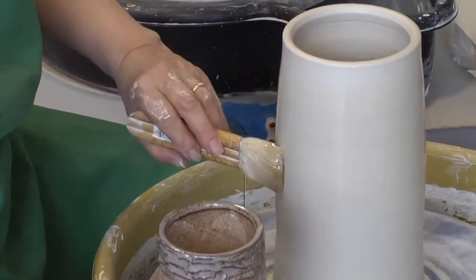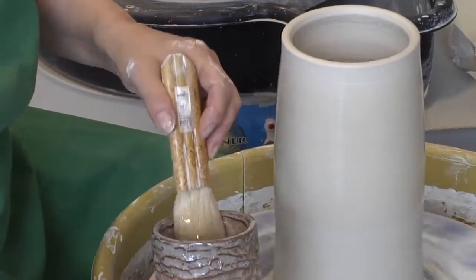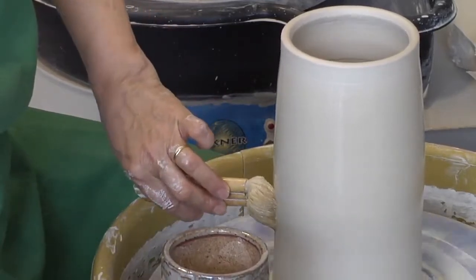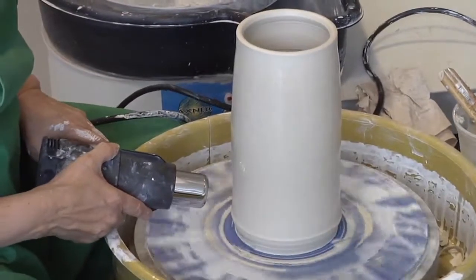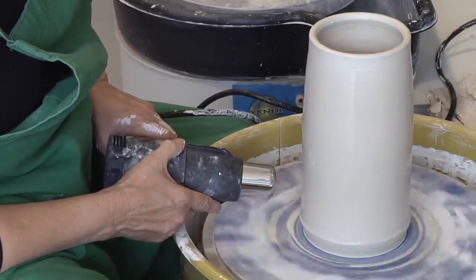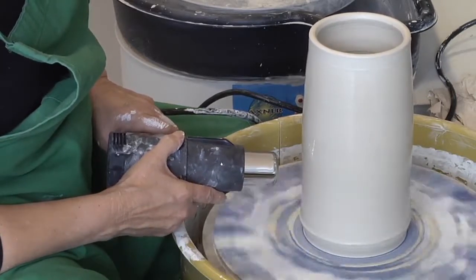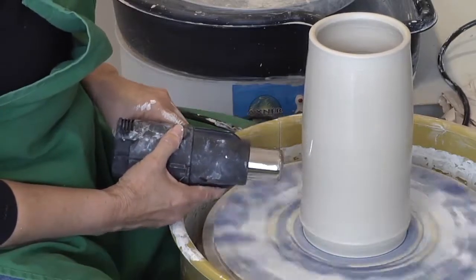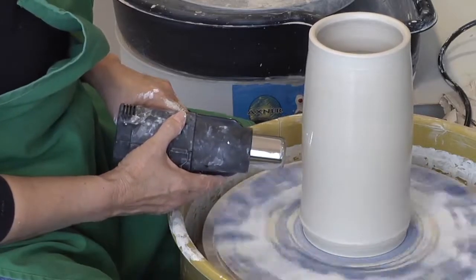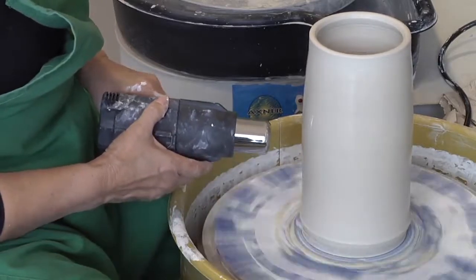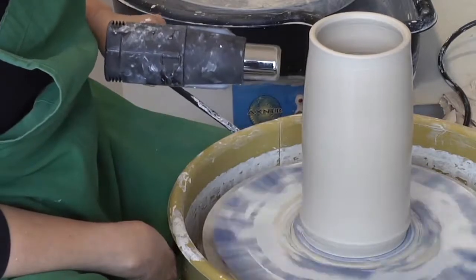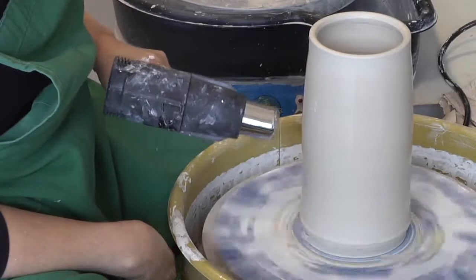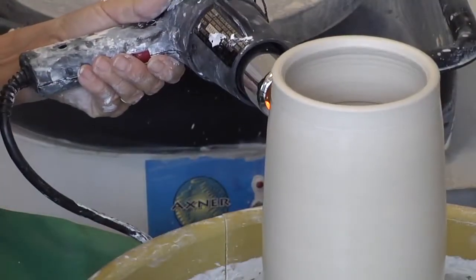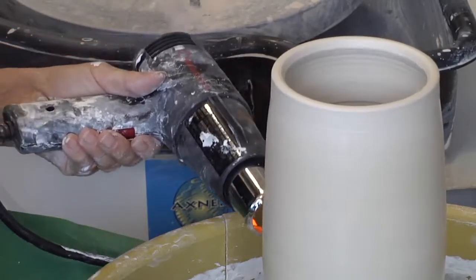So let the pot set up a little bit before I put the sodium silicate on it so that it is not quite so wet, and the sodium silicate will dry faster. And then I'm going to help it along with a heat gun. Okay, so that should be enough. And now I'm going to dry it. So I don't want to see any sheen on there before I start pushing out. It's almost ready.